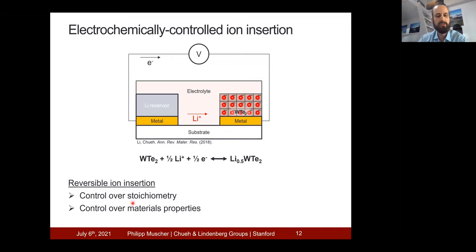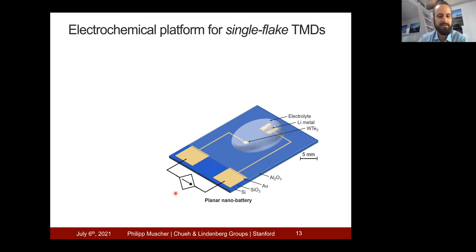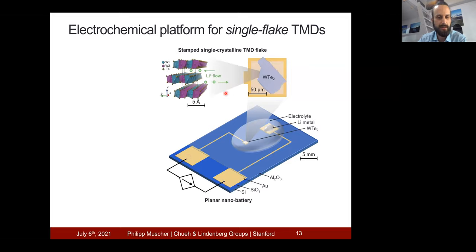So with this, we have control over the stoichiometry of the material, which gives us control over all the material properties that depend on it. So this platform, we wanted to implement for single flakes of tungsten ditelluride. And this I've done by designing this on-chip electrochemical platform. So we have a tungsten ditelluride flake stamped on this current collector. And then we have lithium metal stamped on the other current collector, which is the source of lithium ions. And then I apply an electrolyte on top, which allows ionic flow between these two electrodes. And then we can close the electrical circuit and we can control exactly how many lithium ions are flowing in and out of the van der Waals gap.